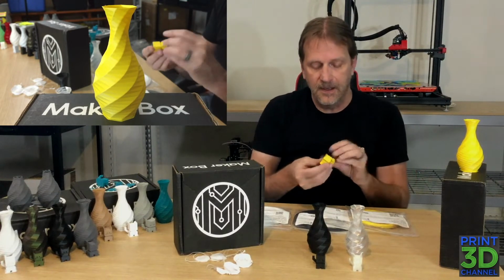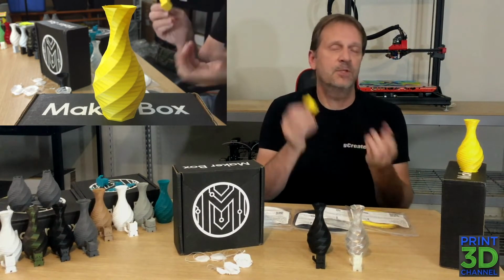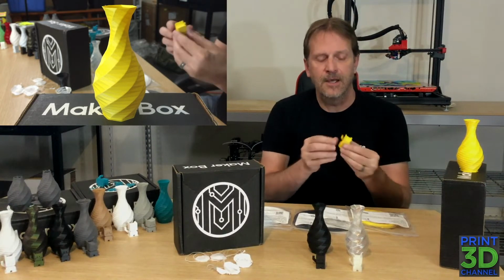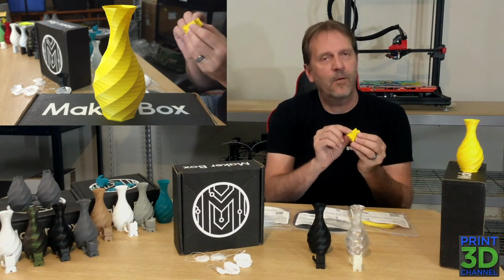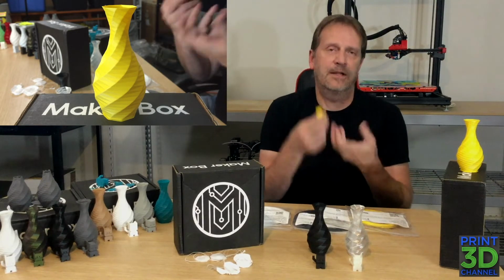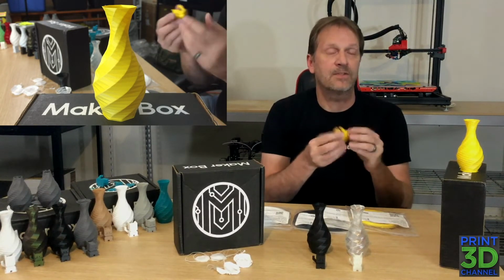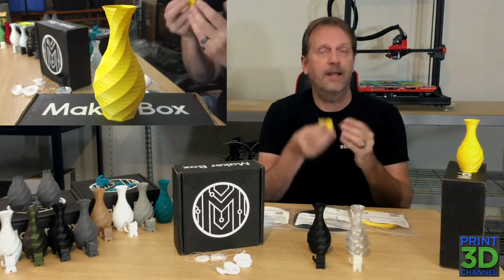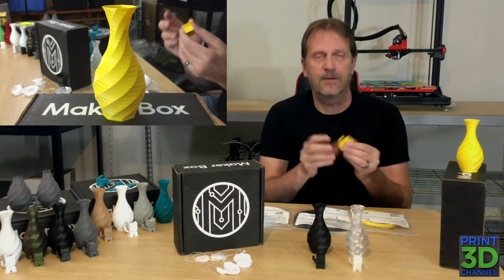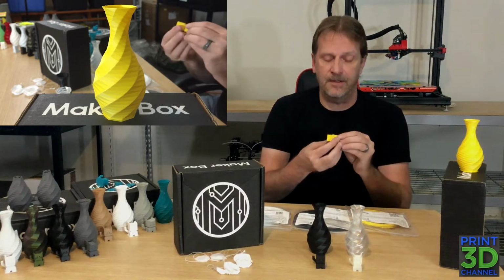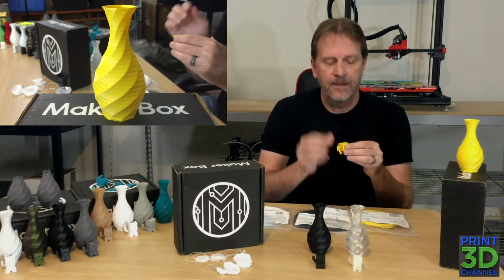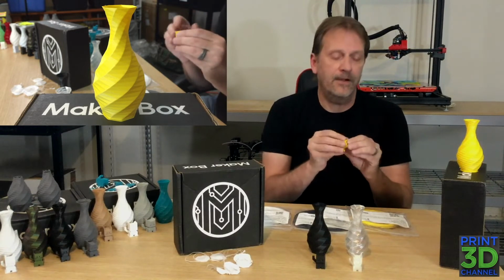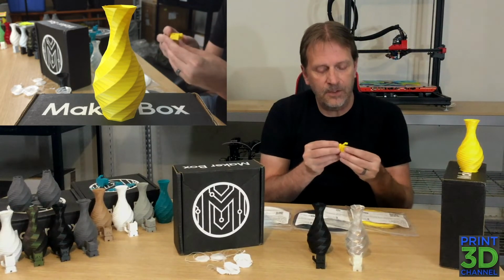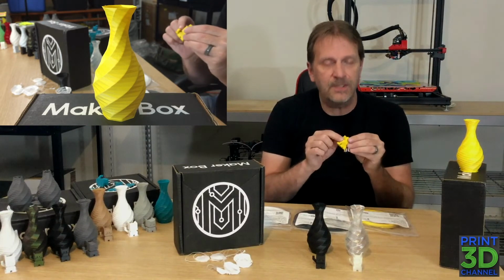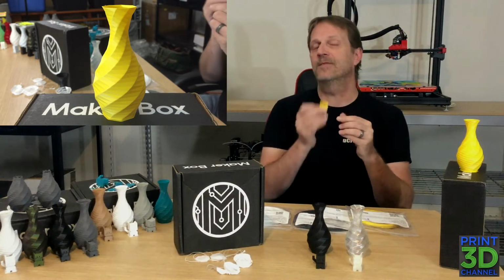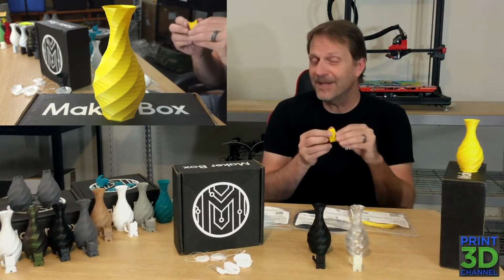Rose Twist Vase. I did have some issues, and that was my temperature adjustment from 215 C to 210 C, because I did see a little bit of that melting going on in the corners here, and that's the normal adjustment. I'll just drop it down 5 degrees, and sometimes I'll increase the cooling depending on the type of filament I use. But I left my cooling at maximum at 60%, and I think that's more than enough for PLA printing. But this Cali Cat turned out awesome. The matte finish will bring out any print errors, and I don't see any on the surface of this. This turned out really great. There is a little bit of stringing between the tail and the body, but I get that on almost every single Cali Cat I print, no matter what the temperature setting is for it.